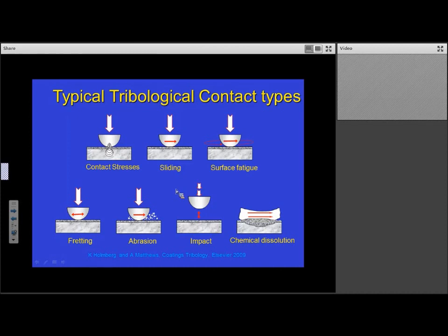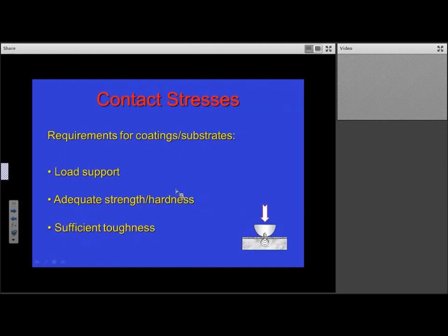and the underlying substrate. So for example, if you have a simple contact stress, a static contact stress, you need load support, you need adequate strength within the coating, adequate hardness, and you need sufficient toughness. So toughness is clearly important. You don't want cracking to occur.